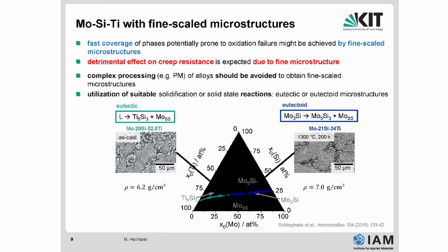The striking feature in this slide, without going too much in detail, is, and this is why it's plotted on a relatively small scale, this is an ultra-fine microstructure in both cases. Here in an as-cast situation and here in a heat-treated situation. And you see already, according to the heat treatment temperature, 1300 degrees Celsius for 200 hours, you need a very high temperature for long times to get the thermodynamically stable two-phase microstructures consisting of those two phases for this alloy.